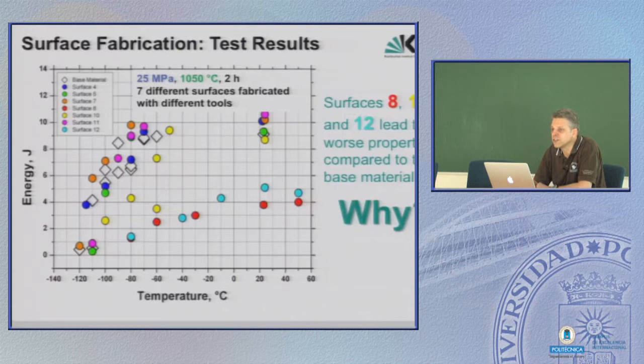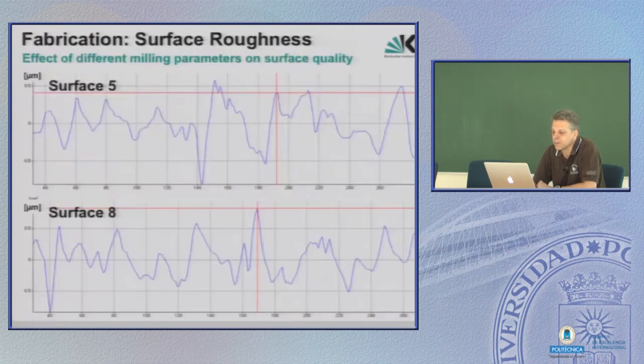And of course, the question first was why? Then, what do you do if you study the influence of surface fabrication? You scan the surface and see how the roughness has or could have an influence on welding. This we have done. This one was a surface which produced a good Charpy result. This one was the surface which produced the bad behavior. And can you see the difference?